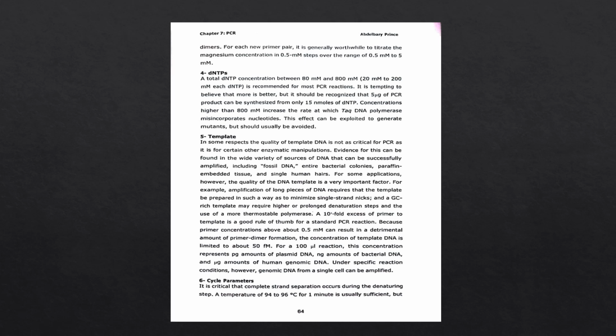Because primer concentration above about 0.5 millimolar can result in a detrimental amount of primer dimer formation. The concentration of template DNA is limited to about 50 fM. For a 100 microliter reaction, this concentration represents a picogram amount of plasmid DNA, a nanogram amount of bacterial DNA, and a microgram amount of human genomic DNA. Under specific reaction conditions, however, genomic DNA from a single cell can be amplified.